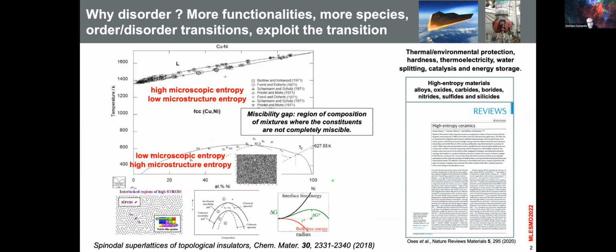This is an example. This is materials science 101. For instance, if you have a copper-nickel alloy, this is a pure FCC copper-rich and pure FCC nickel-rich. If you keep adding species and you are near the center of the phase diagram, you see that you have this line, which is called the miscibility line, which separates the region of mostly order from the region of mostly disorder, right? This is really a schematic.